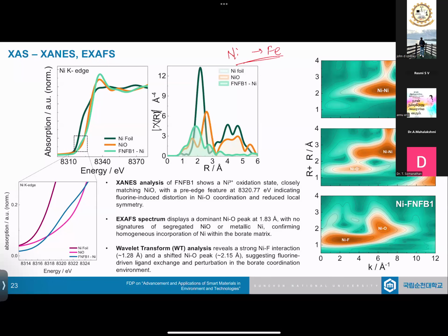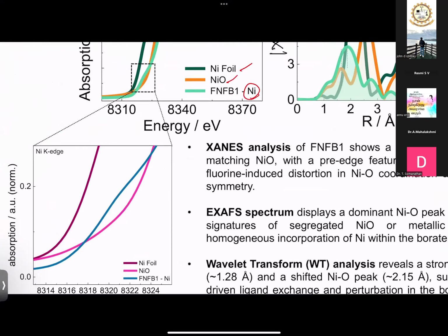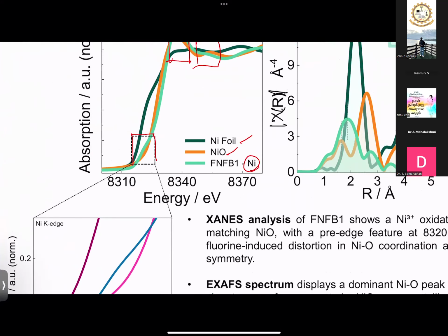So we have the reference data of nickel foil and nickel oxide, and this is the nickel data from our material. You can see that we can confirm through the white line section. This is called the white line section, where it confirms that there is presence of NiO bond, but not a separate bond, and there is no post-edge that's been observed here. But rather there is a pre-edge that's present over here. Pre-edge basically confirms that there is an alteration in the symmetry, in the coordination.